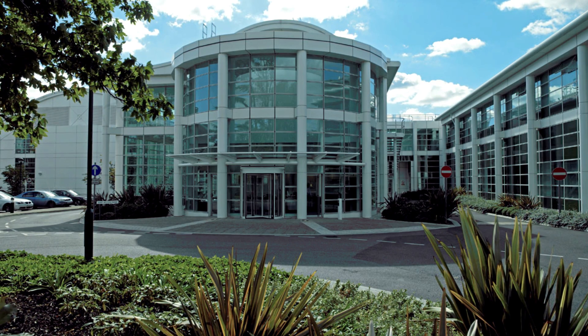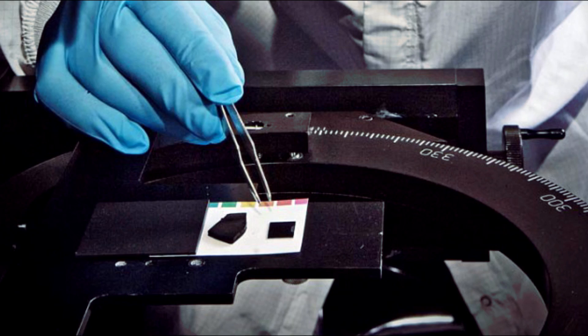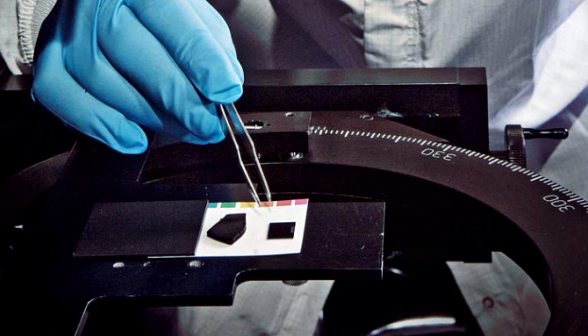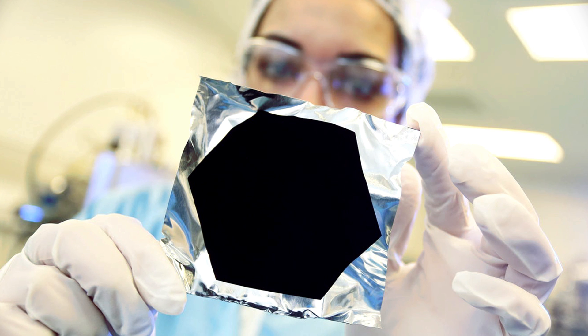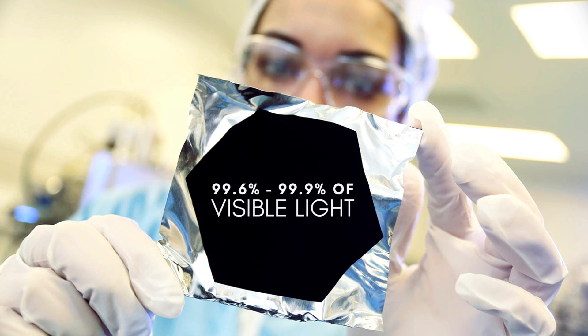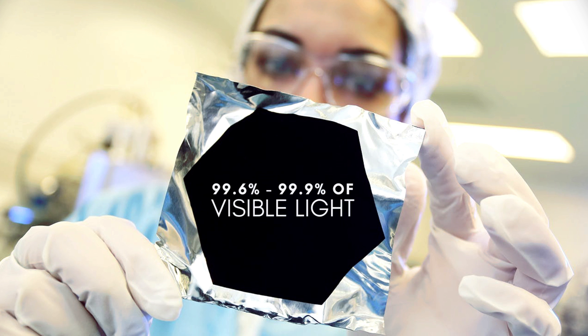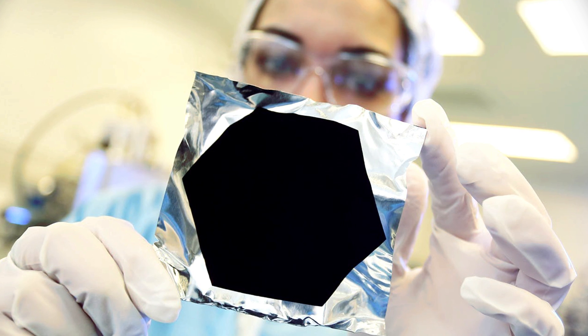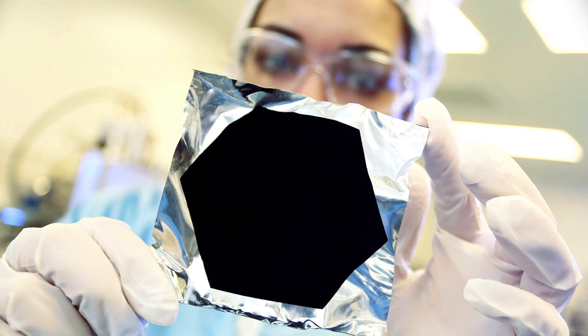The next level of high-absorbing coatings came from the National Physical Laboratory (NPL) in the United Kingdom. Known as super black, this surface treatment is created by first plating a surface with a nickel-phosphorus alloy, then chemically etching it, creating a cratered microstructure. The super black surface treatment was capable of absorbing up to 99.6% of the light that fell on it head-on, and performed even better off-angle, absorbing up to 99.9% of light that fell at a 45-degree angle. Because the super black treatment is only a few microns thick, it suffers from transparency in the infrared spectrum, making it only practical for visible light.